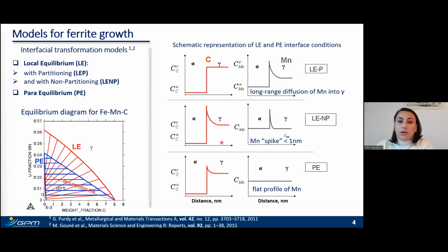And finally, in the case of para-equilibrium, it is assumed the substitutional elements are completely immobile with respect to the time scale of transformation. So there is no partitioning of substitutional elements, and a flat profile of manganese is expected in this case. Despite the fact that this model is one of the most widely used to predict phase transformation kinetics, deviation from this prediction is often reported in the literature. Therefore, more experimental data are required to support or deny this theory.